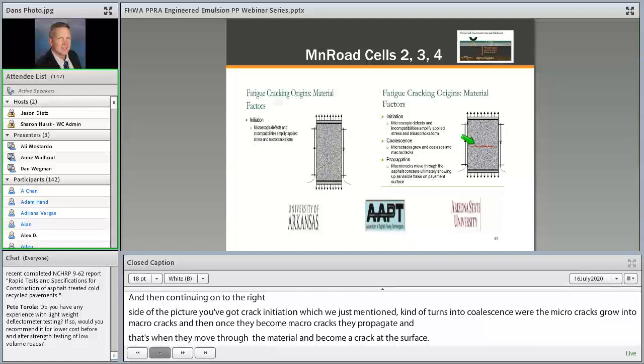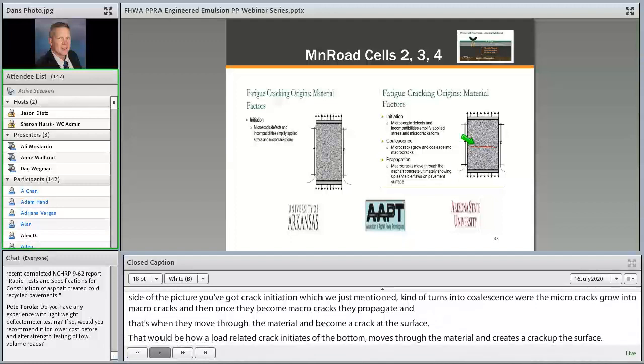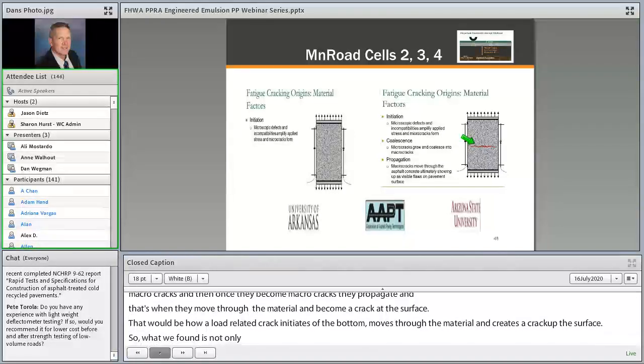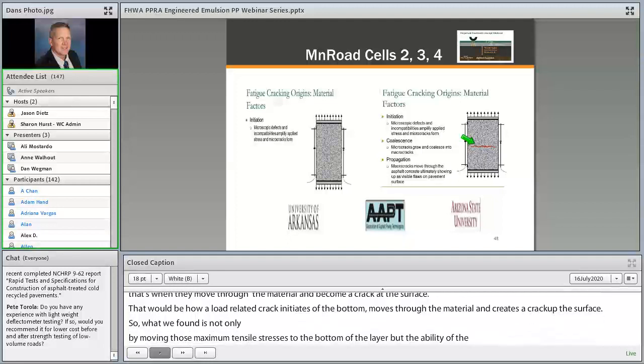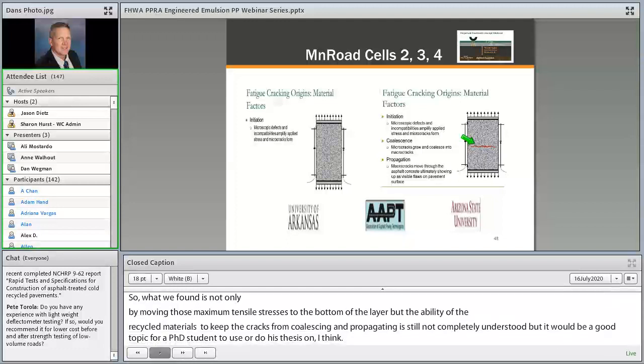So what we found is not only by moving those maximum tensile stresses to the bottom of the bound layer, but the ability of these recycled materials to keep the cracks from coalescing and propagating is still not completely understood, but it would be a good topic for a PhD student to do his thesis on, I think, because I think it's a combination of the unaged binder that's being used in those processes, along with the voids of the cold-in-place materials, because cold-in-place materials have higher voids than hot mix.